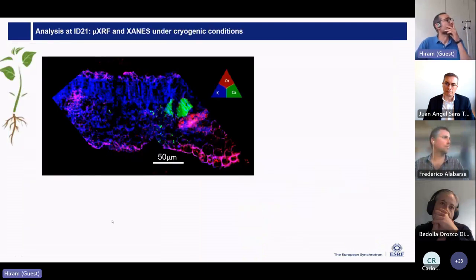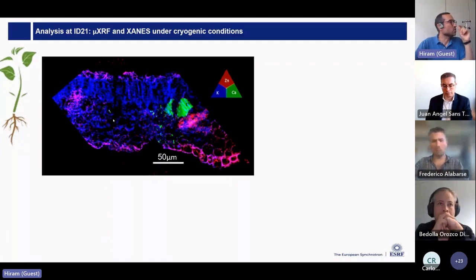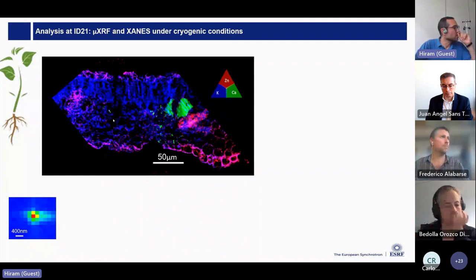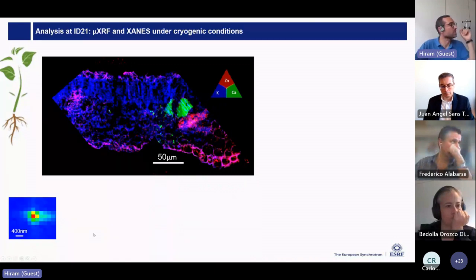So in here, what you see is a map of zinc, calcium, and potassium. You can see zinc was deposited in the upper surface, but it has made it across all the layers of cells in the leaf. This is pepper leaf. And so evidently we are looking at nanoparticles. In some of them, we can see very small hotspots with our resolution right now. This pixel is 200 nanometer.